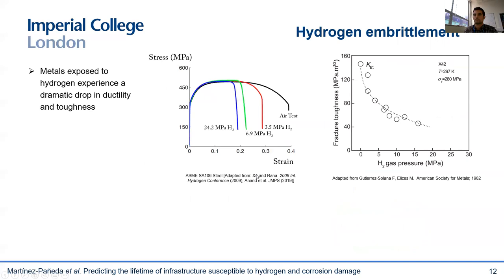Let me start with the modeling of hydrogen embrittlement, which is becoming notoriously important. The issue is that hydrogen is a virus for metals. Metallic materials exposed to hydrogen experience a very significant reduction in ductility and fracture toughness. If we increase the content of hydrogen coming into our metallic samples, we will observe a very noticeable drop in the failure strain, and the same goes for the toughness. In fact, the reduction in fracture toughness can be up to 90% for some alloys.